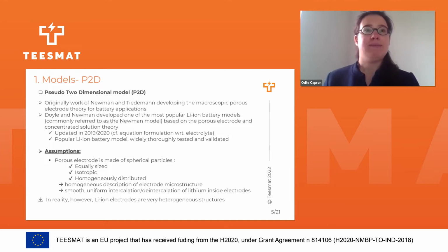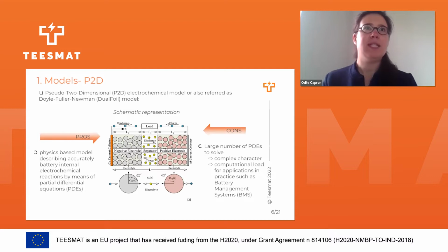So that's also what leads to smooth and uniform intercalation and deintercalation of lithium inside electrodes. So it's quite an ideal case, let's say. But in reality, lithium-ion electrodes are very heterogeneous structures. So that's good to have in mind. These assumptions can be seen now on the graph. That's what I explained. To have a good representation, we have a negative electrode on the left side, positive on the right side, and the separator filled with electrolyte, through which the ions will be moving from one electrode to the other.